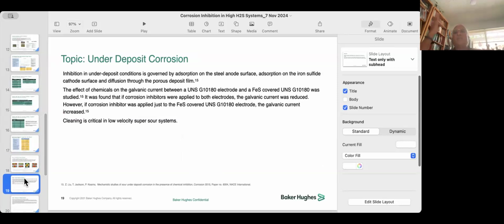So again, under-deposit corrosion is there. There are different ways of, it's really important in actual operation to clean your system. There are galvanic means of looking at these. And again, sometimes in some of these studies, when you apply the corrosion inhibitor, the corrosion can be increased. Now I'm not sure whether these are always, no, these are not artifacts. You have to be very careful.